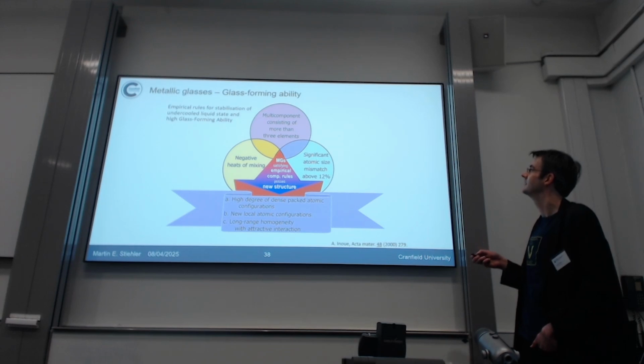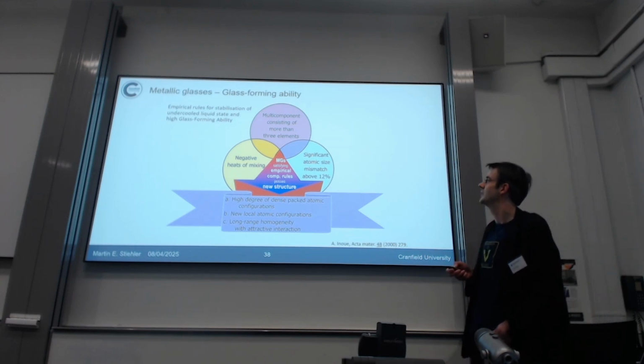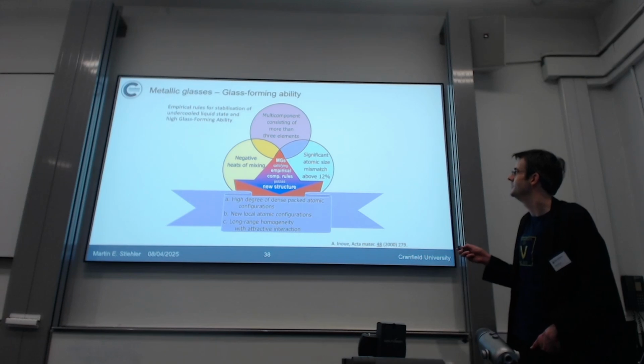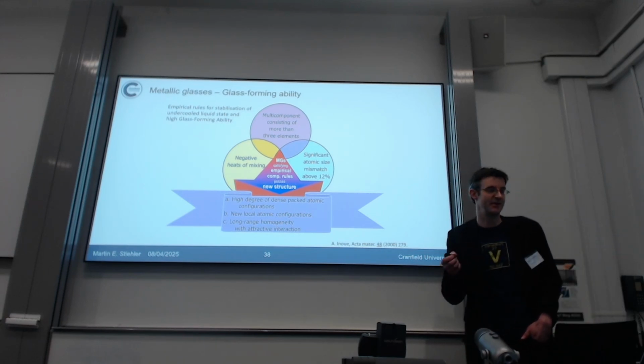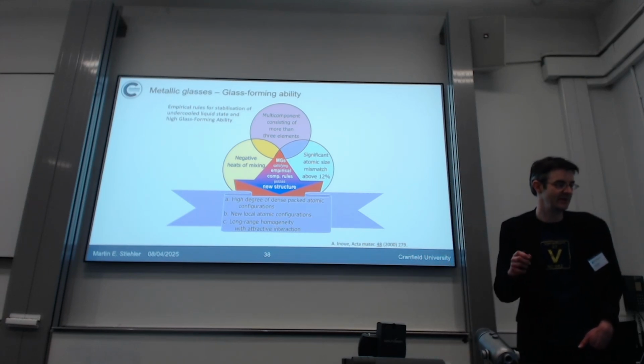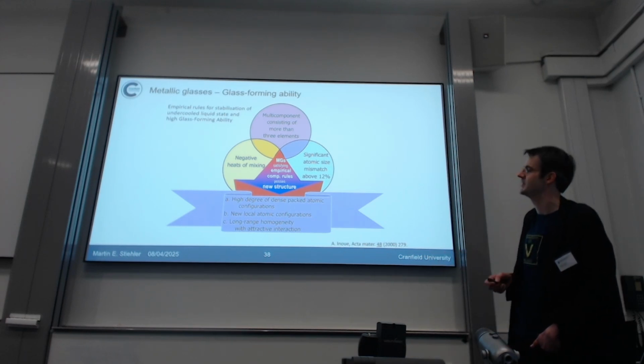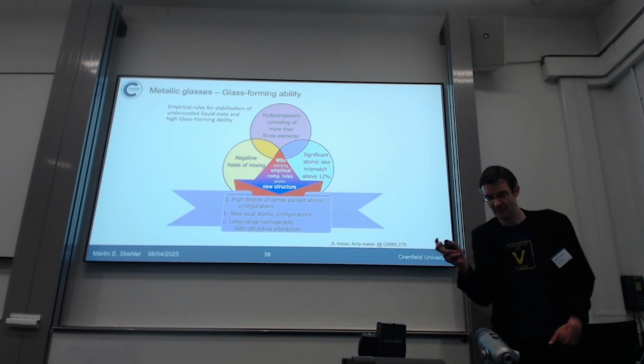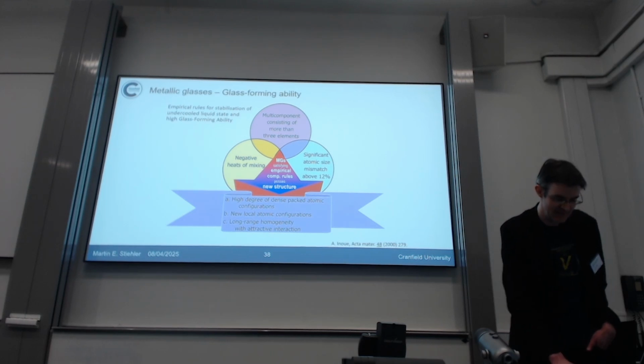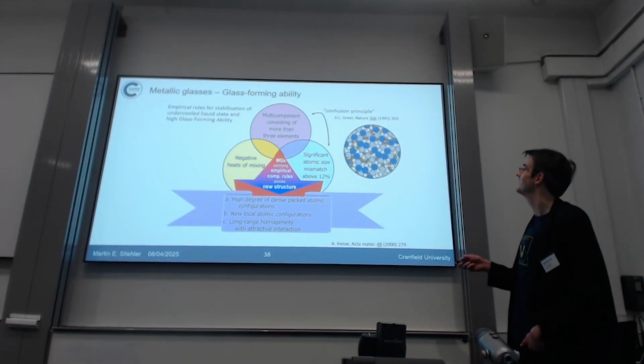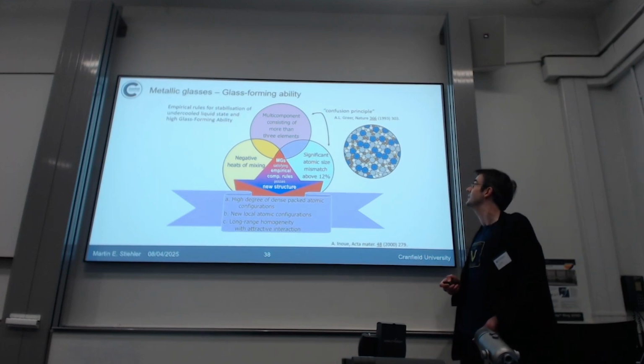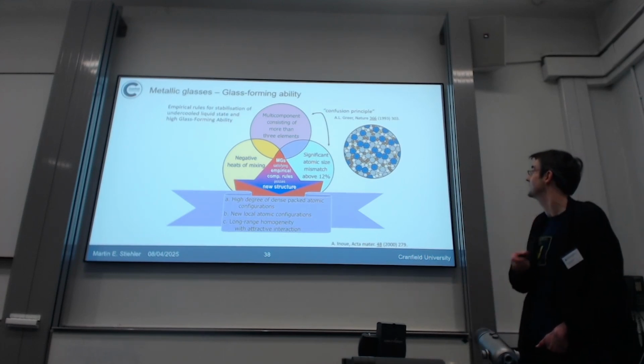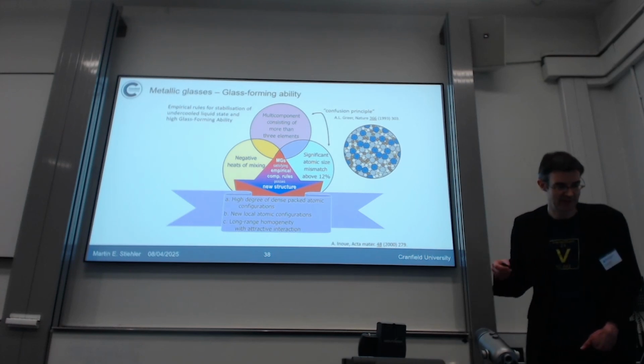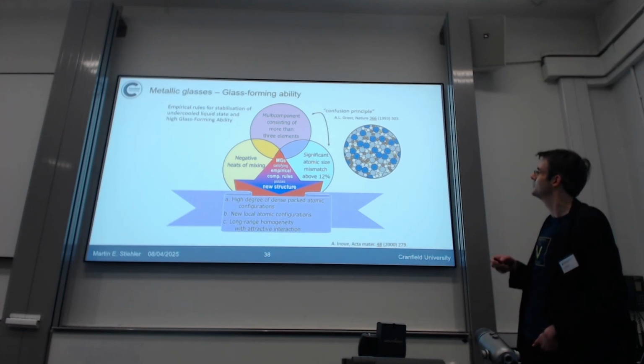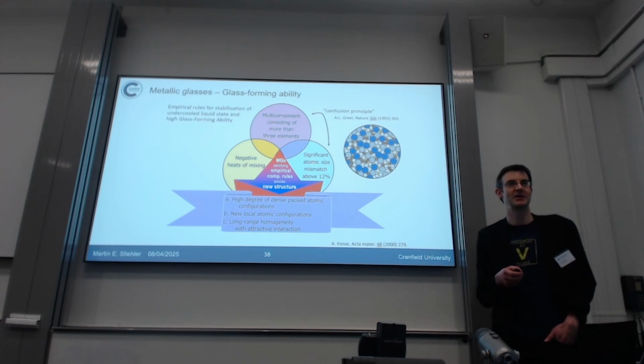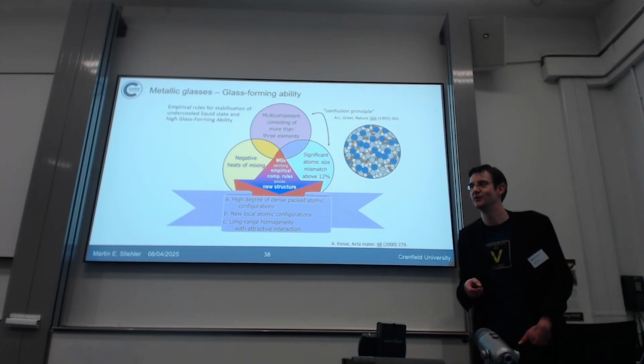And the main rule is, as I said in the beginning, having a multi-component material, and you should have a significant size difference between these different elements, and yes, also would like to have some positive or some good attraction between those species. And these two rules combined is sometimes called the confusion principle after Lindsay Greer. He mentioned that quite some years ago now. So if you have too many atomic sizes, the material doesn't really know what to do, which crystalline structures to adopt, and it just stays amorphous during cooling.